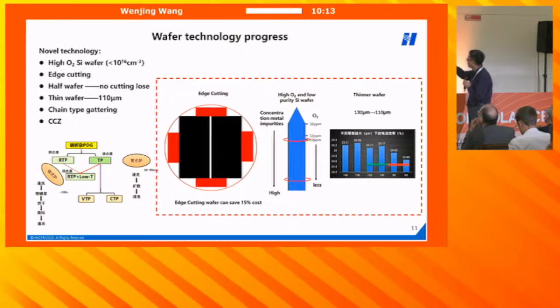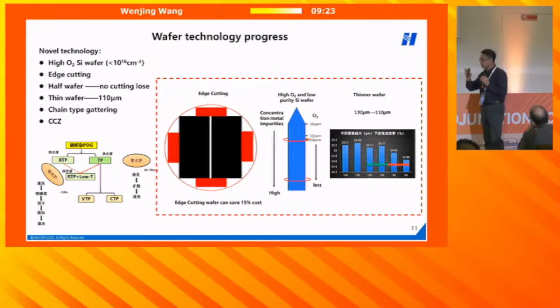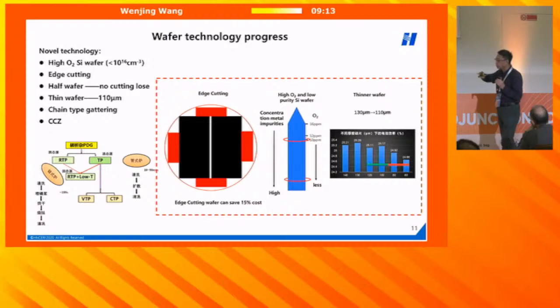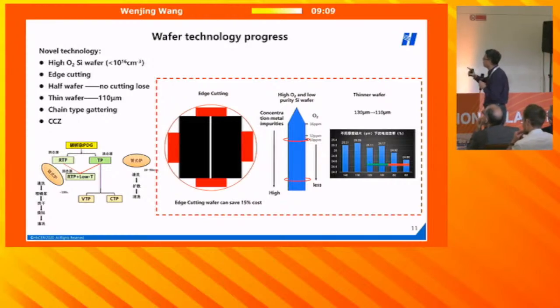And also, we use a half-cutting technology. Before we make a solar cell, we use half-cutting. Because we use the chain process, we can use a half wafer, so we can use edge cutting. For a round ingot, we can get more wafers, and we can use chain gettering. Sorry about the Chinese curve, but this chain process for gettering takes only 2 or 3 minutes to diffuse the phosphorus. If you use traditional tube-type phosphorus diffusion, you have to use 20 to 30 minutes. So from 20 to 30 minutes down to 2 or 3 minutes. It's very quick. So we use a new type of chain gettering system.